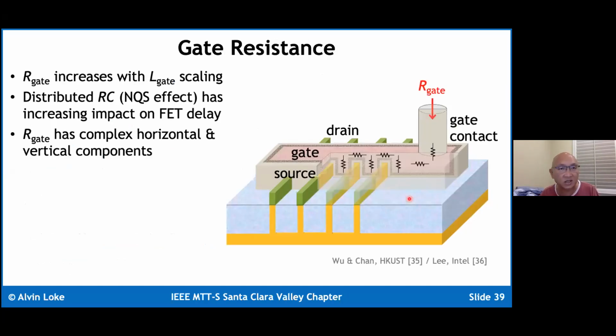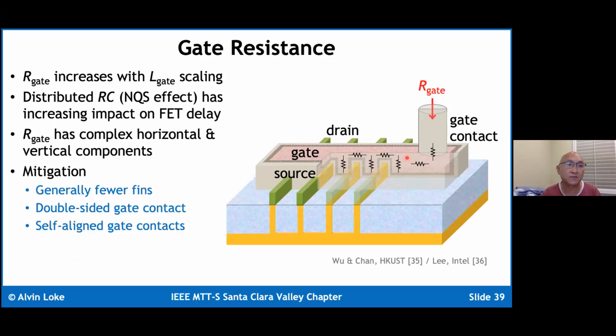Gate resistance, I mentioned earlier, is a significant problem when you scale the gate length. This distributed RC is going to give rise to non-quasi-static effects, which is a big deal, obviously, in RF circuits. There are multiple ways to mitigate this. You can generally use shorter fins so that the distance to the contact is less. You can double side the contact, which is a standard trick to reduce your contact or gate resistance by about a factor of 4. Or if self-aligned gate contacts is available in your technology, take advantage of it.